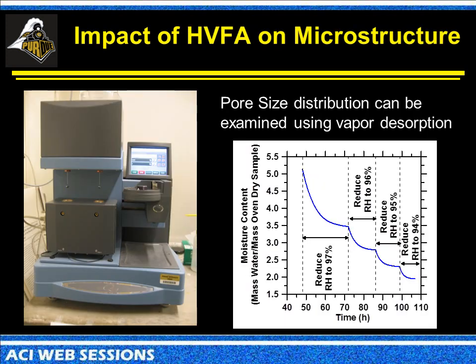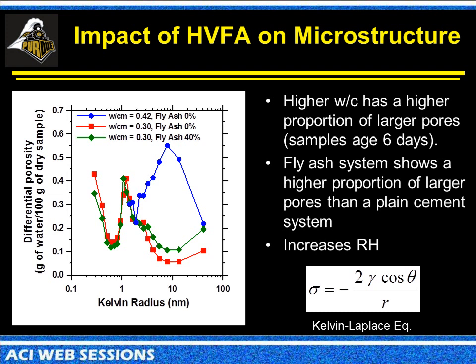But in addition to that, we could go through and we could use water vapor desorption to give us another indication of some of the pore size issues. And here we can actually see the size of the pores plotted along the x-axis on a log scale, and then the size of the porosity over here. One of the things that was interesting to us is we saw a reduction in autogenous shrinkage with the fly ash simply because of the particle size distribution. So having slightly larger pores means that we can reduce the stresses that are developing inside the fluid.